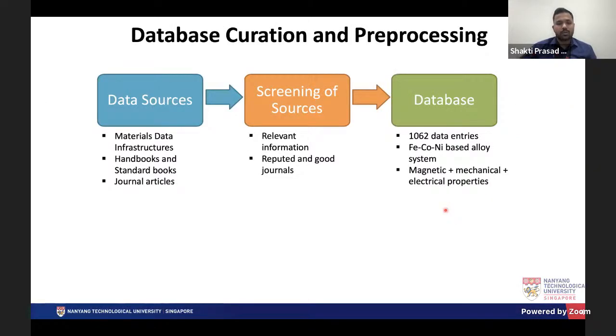So how did I go about it? I collected the data from the literature sources, as shown over here. Then I screened the data for relevant information and from reputed sources. Finally, we had 1062 data entries of iron cobalt nickel based alloy systems with composition and processing conditions. And for the properties, we had magnetic, mechanical, and electrical properties.